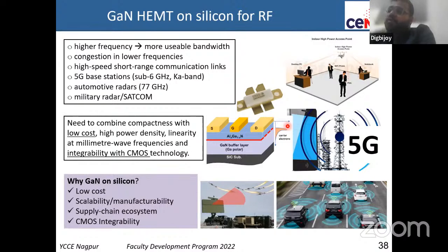Now, gallium nitride for radio frequency application is also being increasingly looked at as GaN on silicon, because you can reduce the price significantly. You can scale it up. For instance, if you want to put gallium nitride in a cell phone amplifier, then the price has to come down. So that's why gallium nitride on silicon is now being actively looked into, because of scalability, manufacturability, and integrability with existing CMOS fabs. So there's a lot of activity at IISc. Also, we are embarking on this work of gallium nitride on silicon platform, where we try to make these devices on silicon. But there are different kinds of problems to address at gigahertz.